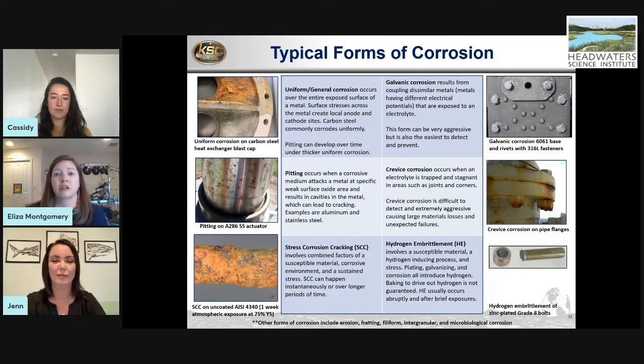We're going to talk a little bit about galvanic corrosion. That is when 2 different metals are together, and they have different potentials. And I'm going to talk a little bit about what that is. That causes one to corrode faster, and the other is protected. In this example, there's a stainless steel bolt and an aluminum plate. All the stainless steel bolts have a little white around them, and that is aluminum corrosion. So at the interface between the stainless, which is perfectly protected, and the aluminum, it's starting to have little dots of white, and those are actually little pits. So that's why this is actually an issue. You can see over time, you would get corrosion of the aluminum, and then the bolts might fall out.